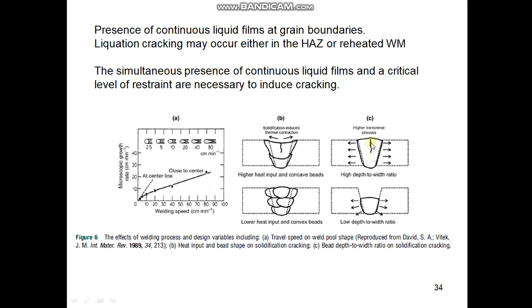The third schematic, C, is about the effect of depth to width ratio. You will see this higher depth to width ratio will face a problem of center line cracking due to high transverse stress. If the depth to width ratio is less, then the shrinkage stresses will be accommodated or taken up by the deposited weld metal. So you have to design your weld joint so that you don't have a higher depth to width ratio. A couple of restraints are necessary to induce the crack. This is in a nutshell.